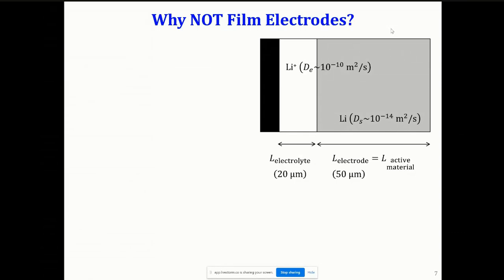Equivalently, at the interface of electrolyte and electrode the reaction will happen. It will convert these lithium ions into lithium, and this lithium would then subsequently get stored in the electrodes. Now it would have its own diffusion coefficient, and its own characteristic length. The two diffusion coefficients I have mentioned are the typical values we see with the materials we have. We see that the electrolyte diffusion is fundamentally faster, about 4 orders of magnitude faster than the diffusion of lithium in the active material phase, which seems intuitive because you would expect solid state diffusion to be slower.